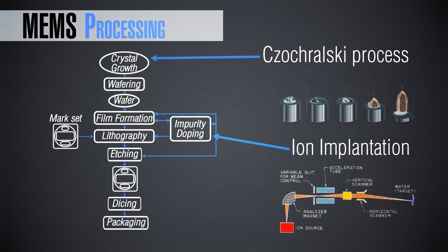There are many issues in this process. For example, you must carefully control the spinning of the molten part, the extraction speed of the rod, the temperature profile, and the uniformity of the chemicals. If you want to grow already-doped crystals, it is easy to have inhomogeneities in the doping level throughout the growing cylinder.